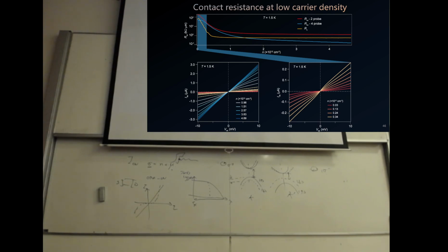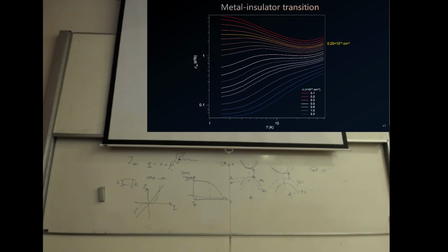So we can just try to use this formula to convert, for example, in 20 Tesla, how much the carrier density corresponds to when nu equals 1, right? So this value is just below that, so we can have some kind of ohmic contact even below the quantum limit. And this is a temperature dependence of resistance of the channel as a function of doping, which is gate voltage. You can see that in the ground state, there is some transition from metal to insulating behavior. And the leveling off one is marked by yellow color.